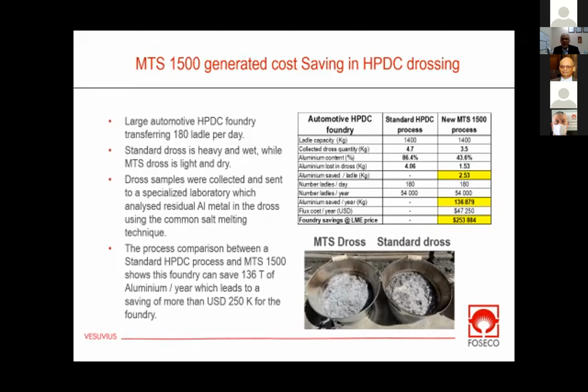They are using very large capacity ladles to transfer the melt from their melter to their casting furnace—1.4 tons. This is very large, and you can see they're doing 180 ladles a day. So this is very high productivity, very high intensity, high pressure die casting.